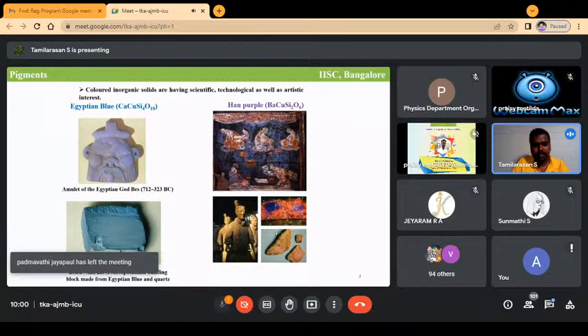So we want a smart material, which we call cool pigments, that selectively absorbs sunlight in the visible region and selectively reflects sunlight in the infrared region. That's a new concept, and we were curious how good our materials would be, and we found that the reflectivity in the IR region for this material, for cobalt doped, was almost 70. For nickel doped it was almost 60, which is very nice compared to copper that doesn't reflect, but still you can see this absorption in the visible region and reflection in the IR region.